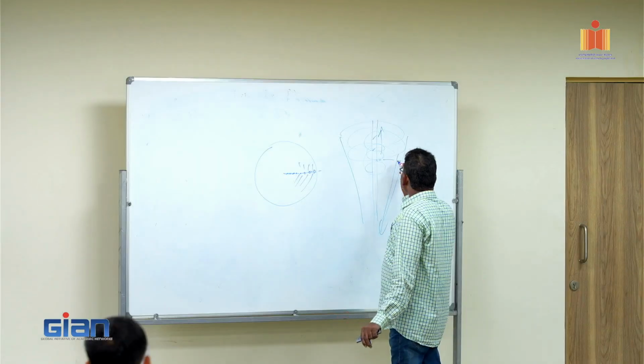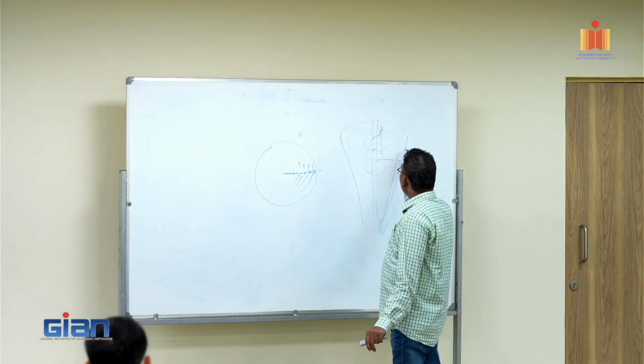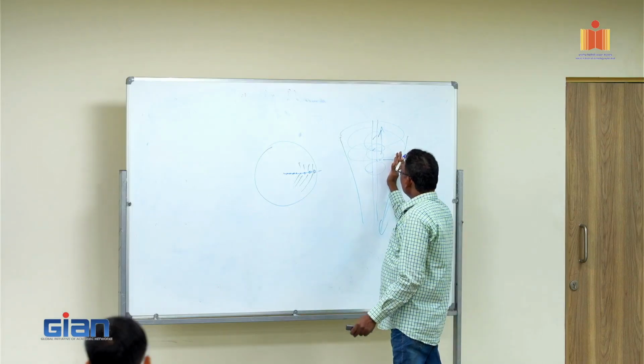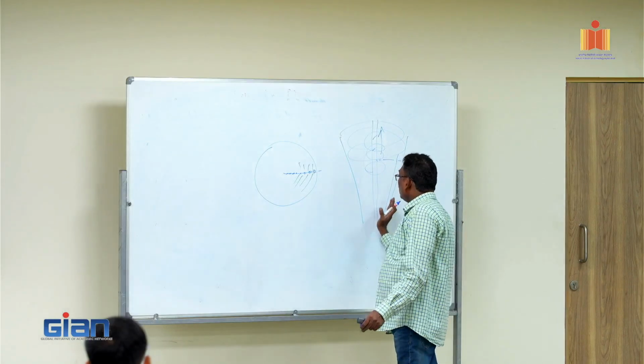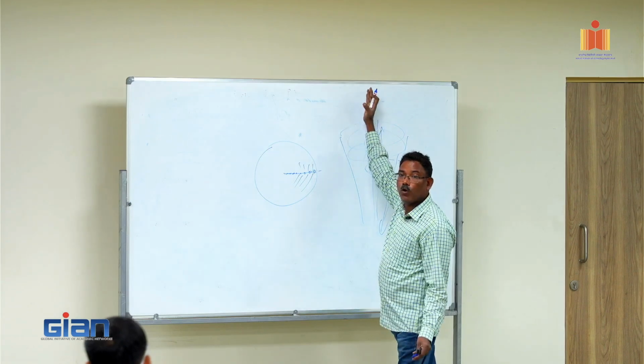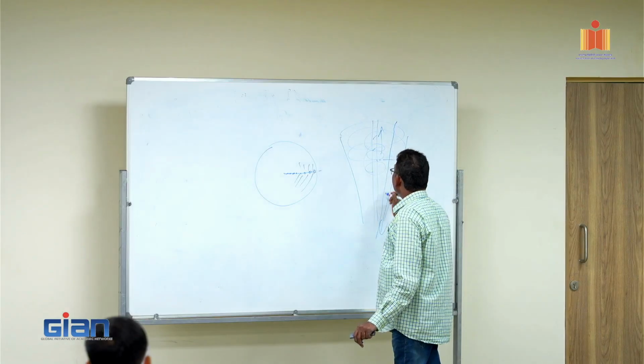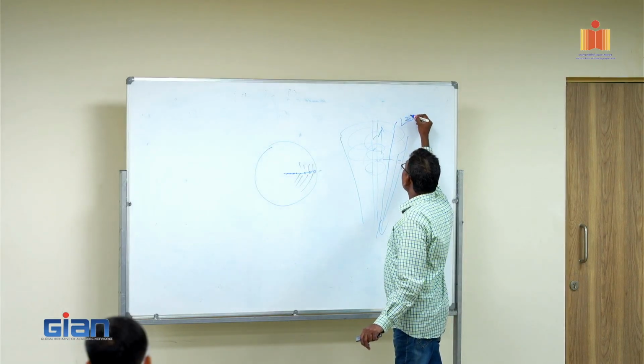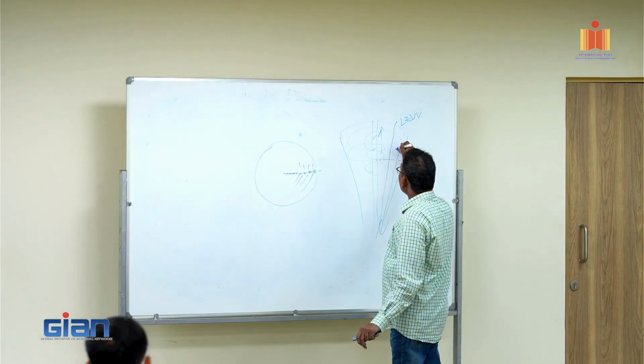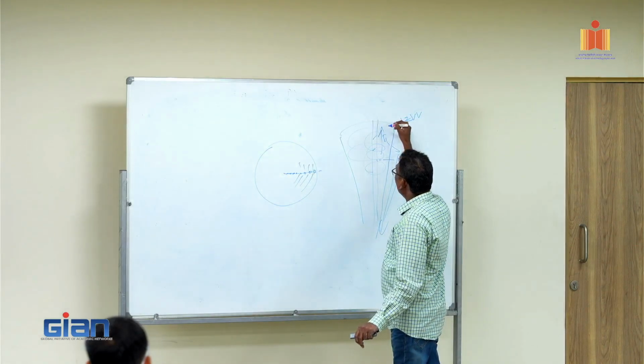So now, once you get it, what happens is one stream of the flow is moving downward and the other stream of the flow is moving upward. Between them, there is a locus of zero vertical velocity. We call it LZVV. On this side of the locus your flow is downward, and on this side the flow is upward.